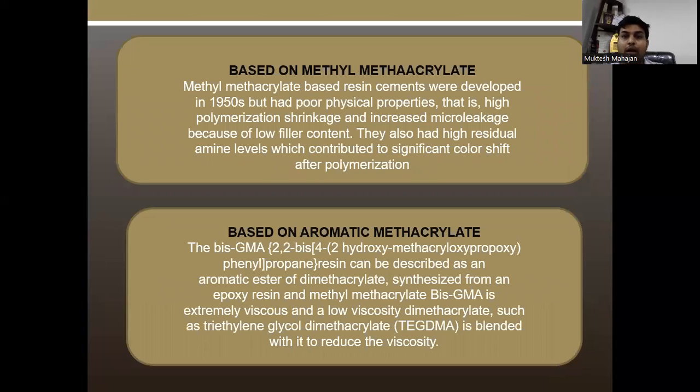Based on the methyl methacrylate, resin cements were developed in the 1950s but had poor physical properties, that is high polymerization shrinkage and increased microleakage because of the low filler content. They also had high residual amine levels, which contributed to significant color shift after polymerization. Based on the aromatic methacrylate, the